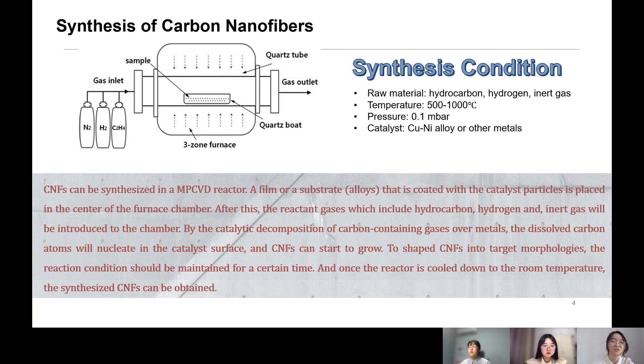After this, the reactant gases which include hydrogen, hydrocarbon, and inert gas will be introduced to the chamber. By the catalytic decomposition of carbon-containing gases over those metals, the dissolved carbon atoms will nucleate in catalyst surface, and then the carbon nanofibers can start to grow.